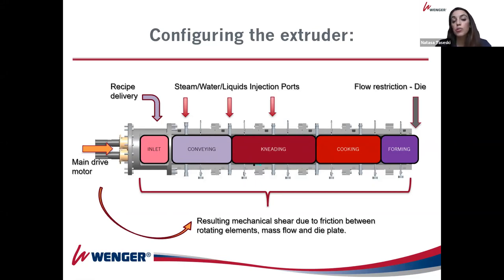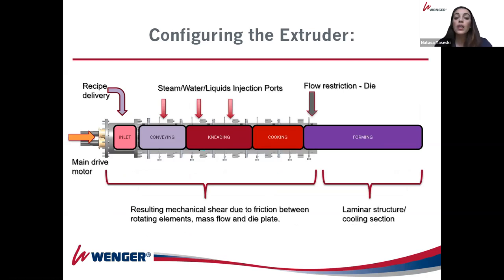And due to pressure difference coming from the extruder into atmospheric, you get expansion of your product. The kind of expansion that you create, and also the kind of texture and direction of fiber formation or expansion or bubbles, is really dependent on the kind of die configuration and die design you have here at the end. When it comes to configuring the extruder for high moisture analogs, the process is also very similar.